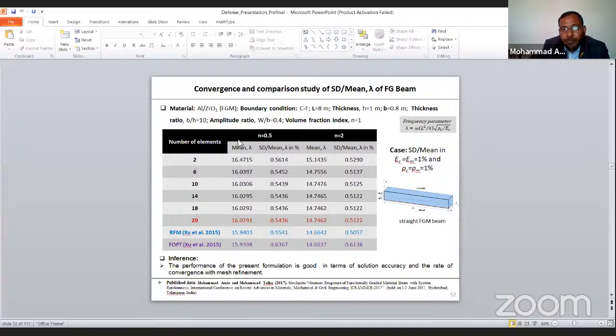and the mean values, that is the deterministic frequency response, as well as the stochastic component, their deviation from the mean values, is calculated. We found that by increasing the volume fraction the randomness in the response will obviously increase, and for this case the randomness is 0.54% for n equal to 0.5, and we compared our result with the existing results. Those results are based on the first order perturbation method as well as the random factor method.